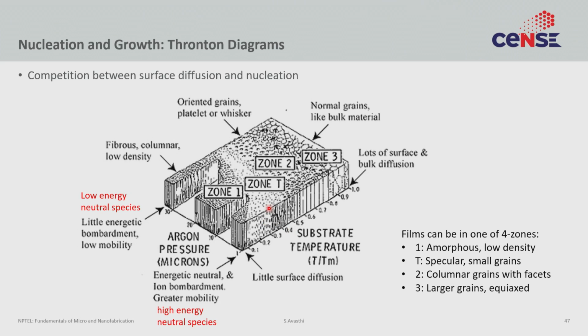Now the thing to understand additionally, the complication that is on top of that, is the effect of pressure. So as you increase the pressure, the mean free path becomes smaller. As the mean free path becomes smaller, the atoms suffer more collisions and thereby lose more energy. So as you reduce the pressure, you increase the energy of the incoming atoms. Because they have higher energy, they can do what could have been done at a high temperature, right? So one way to think about it, as you are reducing the pressure, the temperature at which you do zone T tends to reduce, because you now have higher energy.